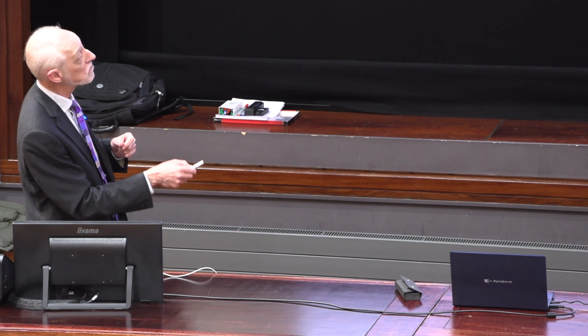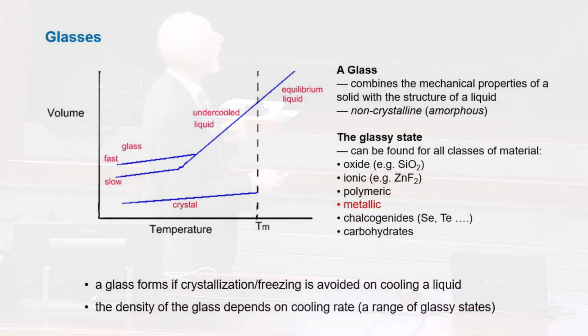So the point I want to get you thinking is that a glass, in this way of looking at it, doesn't rely on it being a particular chemistry of material. You are familiar with window glass, wine bottle glass, etc. But you could make glasses out of pretty much anything. And for a long time, it was not considered that you could make a metallic glass, for the reason that these crystal structures are so extremely simple. So obviously, they can form very easily in the liquid. But you can make a metallic glass. You have to avoid the crystallization or freezing, and you get a range of states depending on how fast you cool. We'll come back to that concept.